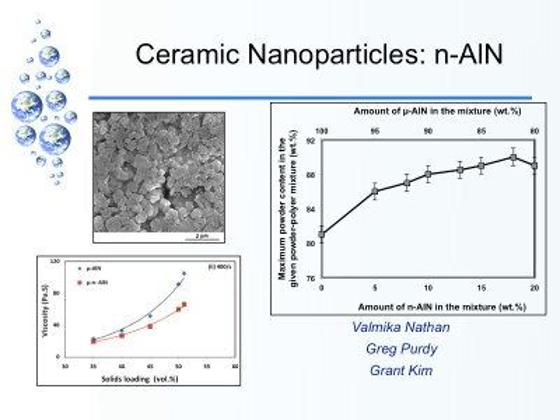The blue beads are just microscale aluminum nitride, about 0.8 microns. Now if you fill the space with nanoparticles, you increase the maximum packing fraction. And so for any given packing fraction, you have lower viscosity for the bimodal system, right? As we had seen earlier, if you increase maximum packing fraction, you will reduce the viscosity for any given volume fraction. As you increase the volume fraction, of course, viscosity will increase, right? So you have two possibilities now. You can either be at the same volume fraction of powder and just get better processability, or you can go all the way up to 72 volume percent, and so you can get much better structures in terms of controlling the dimensions when the material gets sintered. So you can control sintering shrinkage, right?